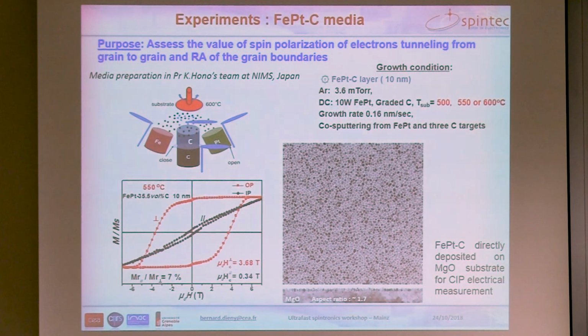tunneling through the grain boundary. And I am going to explain now how experimentally we have determined the polarization of the electrons tunneling through carbon in actual media. So the media that we investigated was deposited at NIMS in Tsukuba in Professor Hono's team by co-sputtering of iron, platinum, carbon.